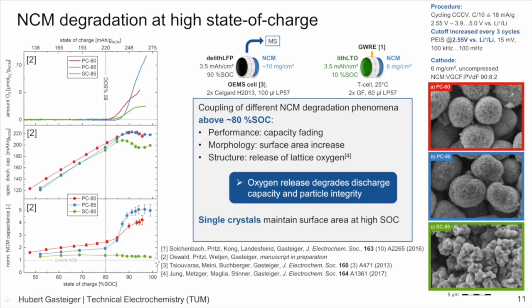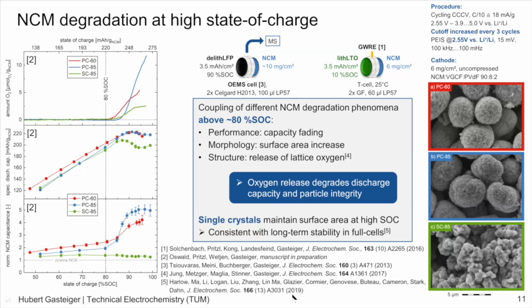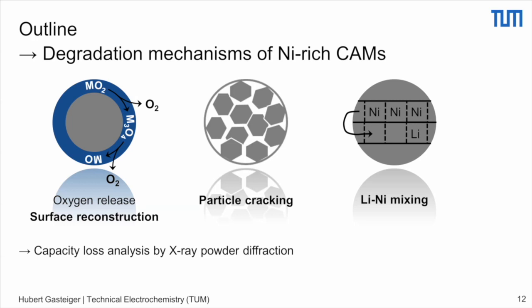And this, of course, also supports the idea that particle cracking mostly happens at the interfaces between the single crystallites in the polycrystalline material. And since you don't have these single crystallite interfaces in the single crystals, the surface area stays quite constant. And this is, of course, consistent with the long-term stability which has been reported in full cells by the group of Jeff Dahn. Okay, so then the next part, we will look at analyzing some of these degradation mechanisms by using X-ray